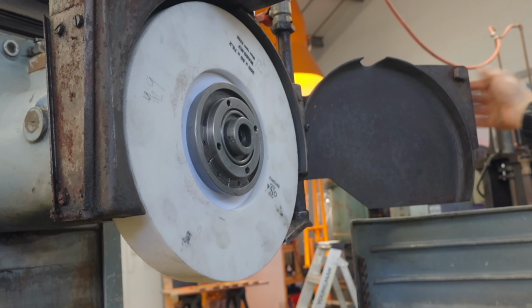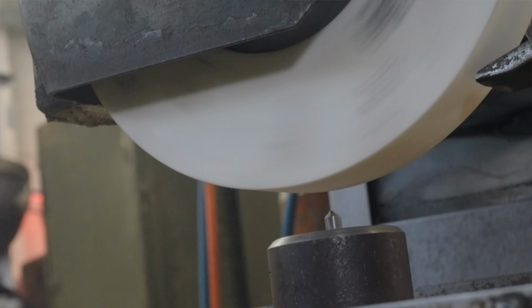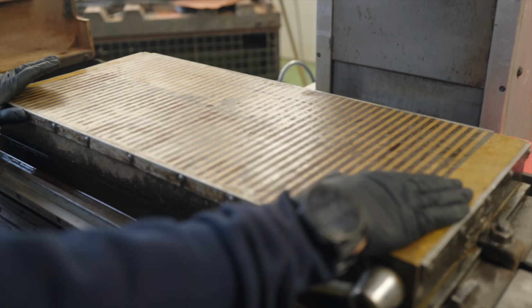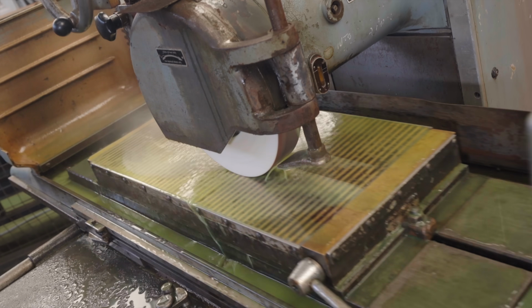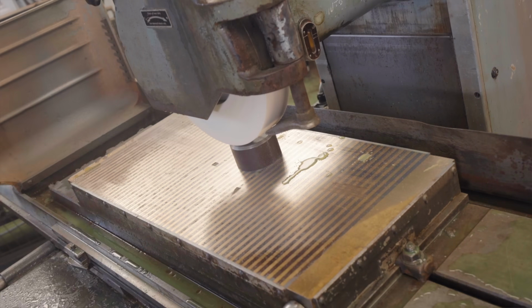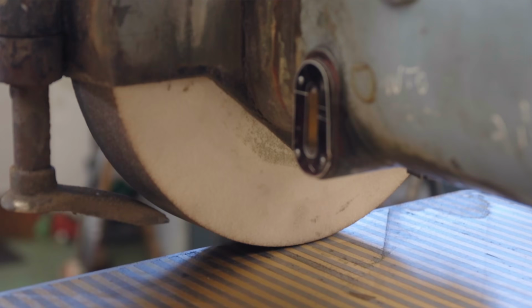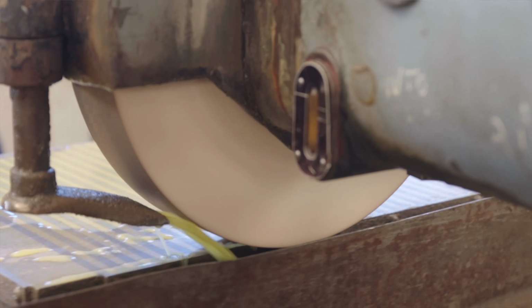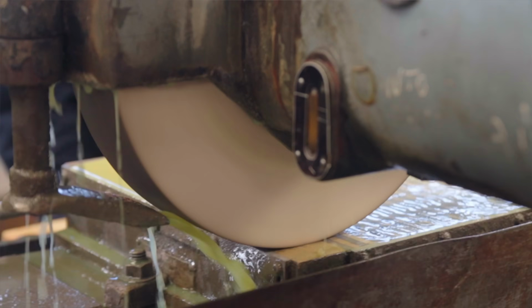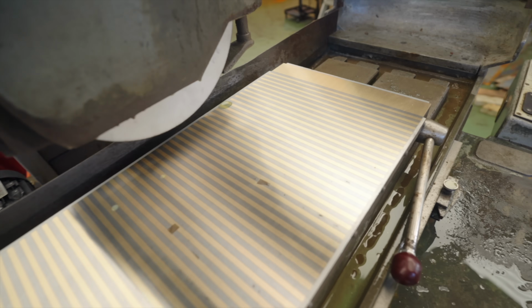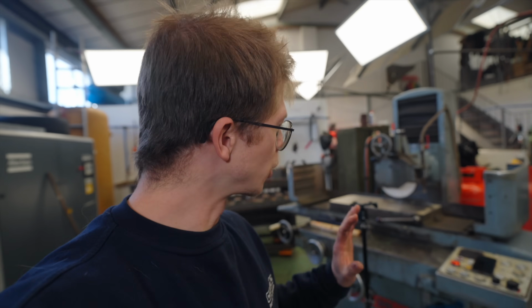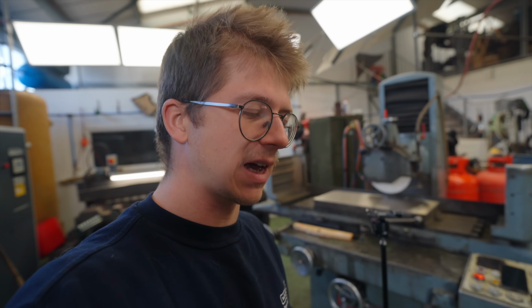onto the machine, where the first thing that we grind isn't any workpiece, it is in fact the magnetic chuck, which is currently rusted, corroded, and nasty. We need to grind it true to the action of the table, and only when that is done and we redress the wheel can we get those bits of material on here. Shiny. Apart from these spots, but I don't see any sense in getting all the way down to the level of that. Just thinning out the mag chuck for little gain at that point. These go over there.